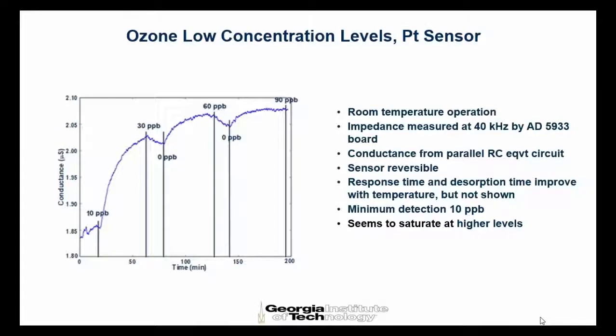What I'm doing here is a platinum decorated nanotube sensor. We are cycling the ozone level from 10 parts per billion to 90 parts per billion, so 10, 30, 60, and 90. But before we introduce the subsequent concentration, we try to retract or dissolve the ozone. So there is a little bit of going back to the baseline, 0 parts per billion. But this is the first measurement that we did.